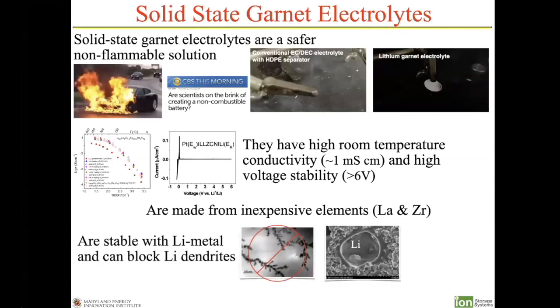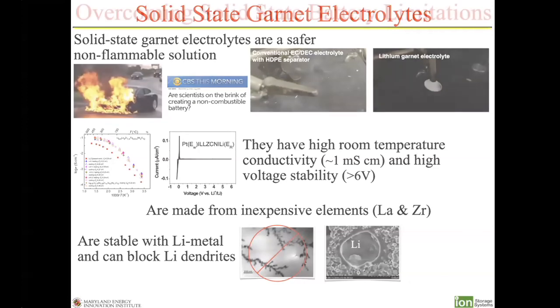But the other aspect of it, again, is that it enables that lithium metal anode. It's stable, again, with the lithium metal, but also if it's processed in the right structure, it can block lithium dendrites. And so the figure to the left with the red through it is your typical polymer or organic electrolyte. You can see lithium dendrites propagating through, causing a short. In the case of the garnet, which you're seeing right now, is a pore in the garnet filled with lithium metal. And I'll come back to that in a minute.